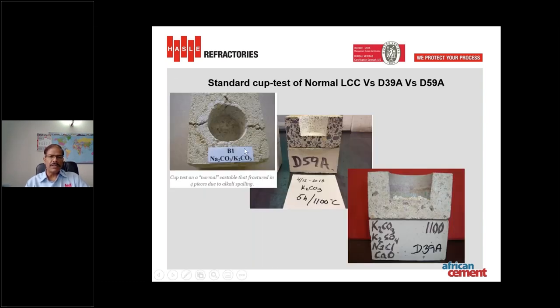We do this cup test in our laboratory. Here you can see the normal castable where we did this alkali test, and you can see this cup is broken, fractured into four parts. But if you are using suitable products, like a refractory with good quality raw materials and good characteristics, then it is not very much impacted by these alkali sulfates and chlorides.